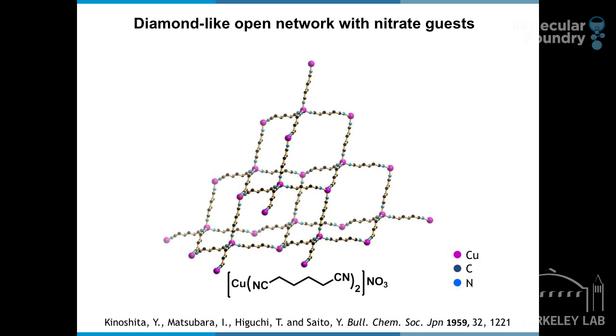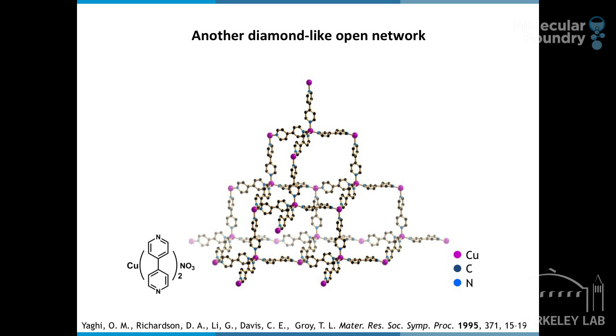Many examples in the literature have been made since then. And when I became assistant professor at Arizona State University, I also entered the field by linking bipyridine with copper-1 to make similarly a diamond-like framework. Except upon attempts to exploit the porosity, in this case by exchanging the nitrates with other ions, we found that the structures were very frail and they collapsed. So we set out to find a new strategy for building rigid metal organic frameworks that can maintain their porosity even in the absence of any guests.